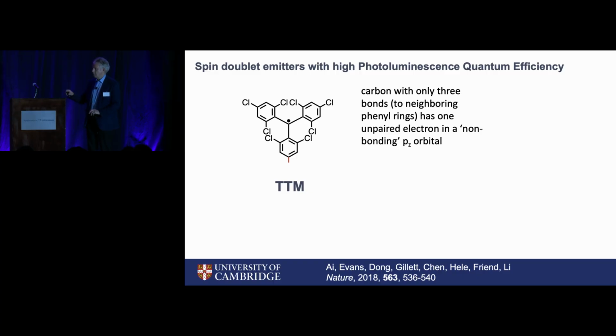If you want to avoid chemistry, you need to wrap them up so that if they bump into one another, the two radical sites are too far away from one another to do covalent chemistry. And this triphenylmethyl structure wraps itself up in a chiral little propeller, and it's been known for a very long time as quite a stable radical. But most of the literature on radicals is that they're dark.